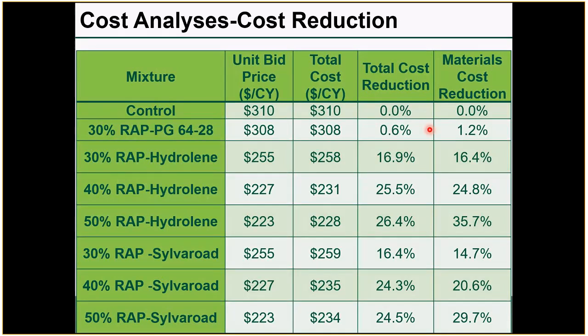So the total cost reduction, based on the bid price, you can see that with a 50%, you're expecting about 25% reduction in cost as compared to the control, and very important, the control here is the 20% RAP in the field. And one of the things that I want to mention here is that the PG64-28, in terms of performance so far in the field, whether it is the cores or the tests done on the lab compacted field produced, it's showing good performance.